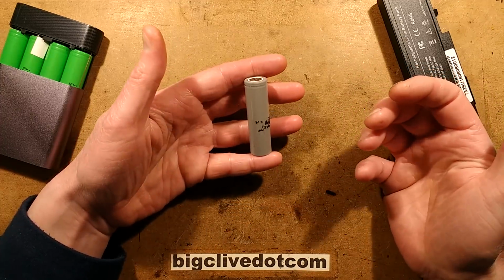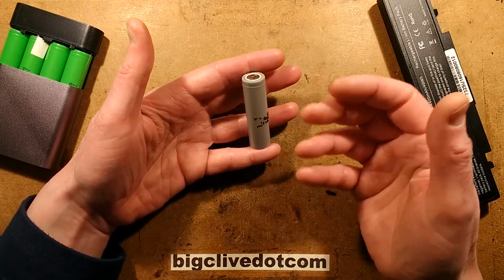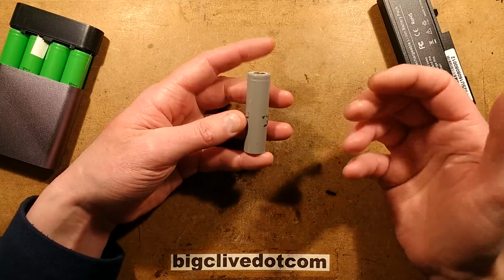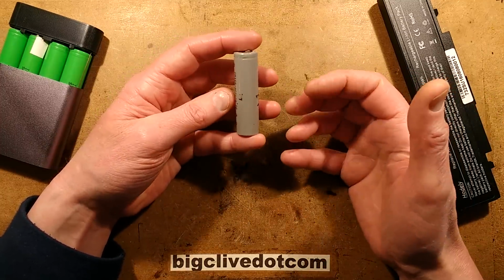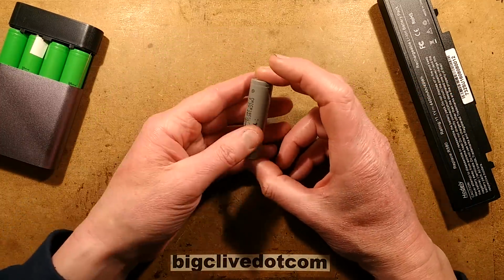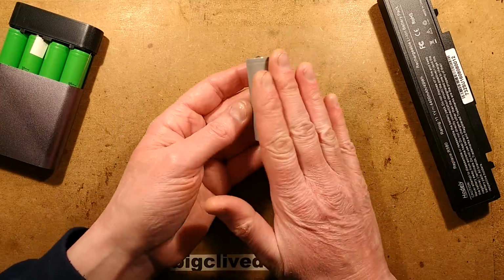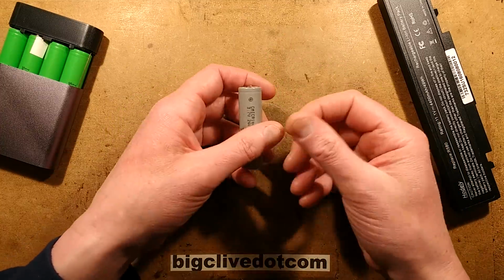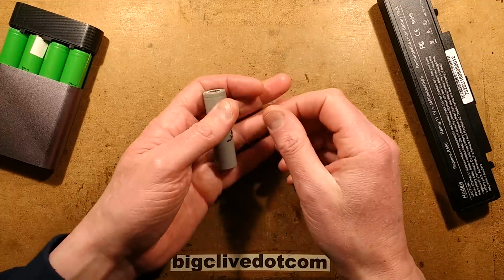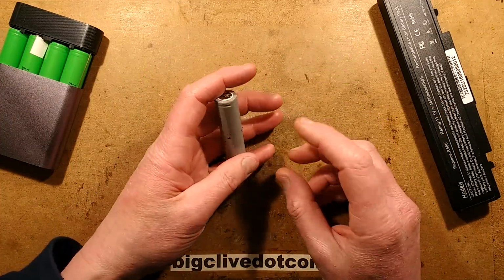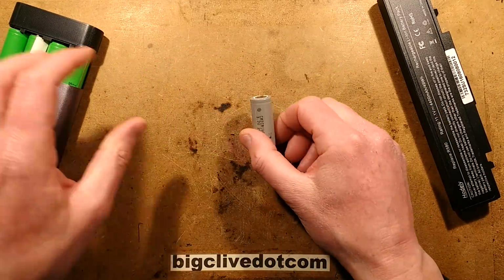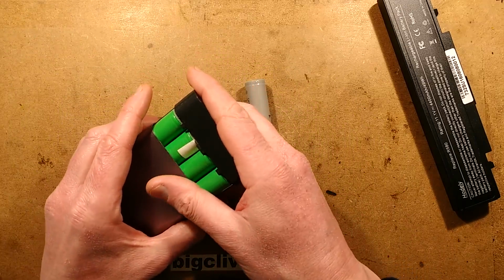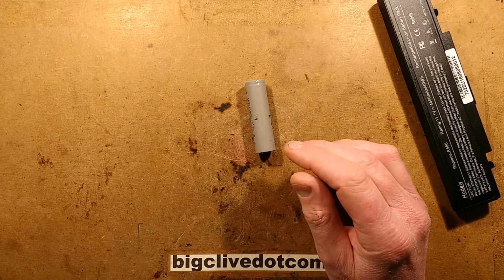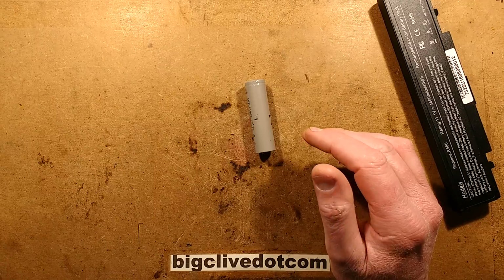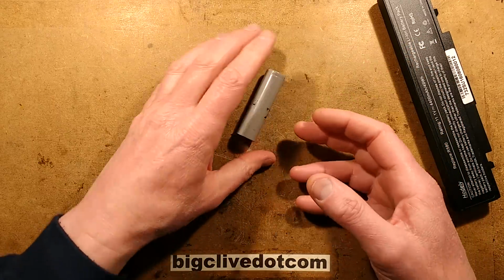It's when you actually reverse charge it with the opposite polarity that problems start occurring, that metal starts flowing from the electrodes and it violates the insulation of the separator. And I took that one apart, and despite the fact that the graphite-type material had stuck onto the separator, there was nothing really obvious. But Ross went further. Ross grossly over-discharged one by several hours at up to 4 amps current because he wanted to see if it really had much of an effect.